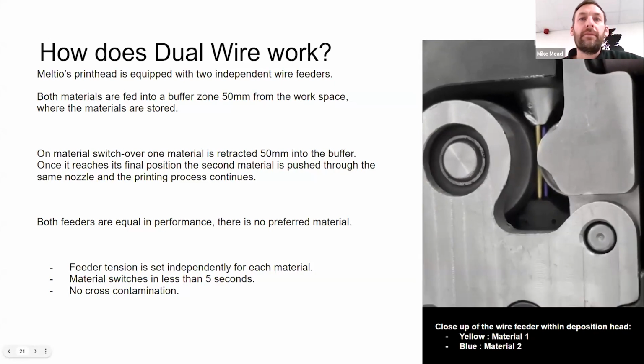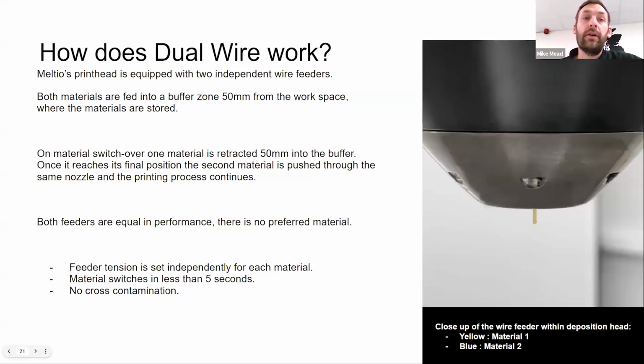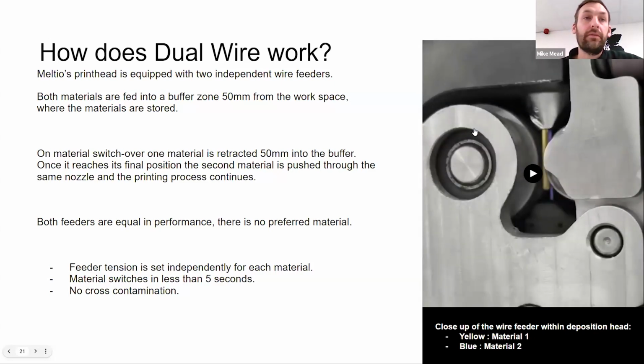Each wire can be independently tensioned so that for softer wires, things like that, we can ensure the tension for the print. And a material change will take around 5 seconds. So this is live on the video. You can see how quickly that can be changed over. We'll get no cross-contamination from the two materials. And as long as the materials selected bond well together, you'll have no problems within your print.